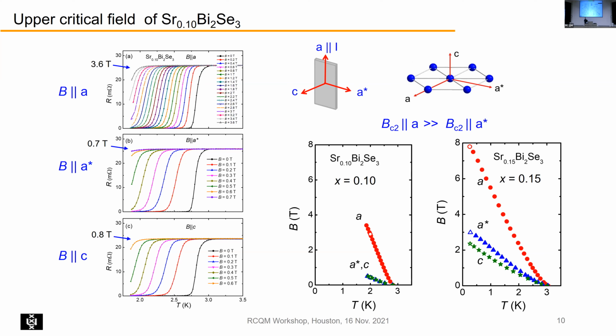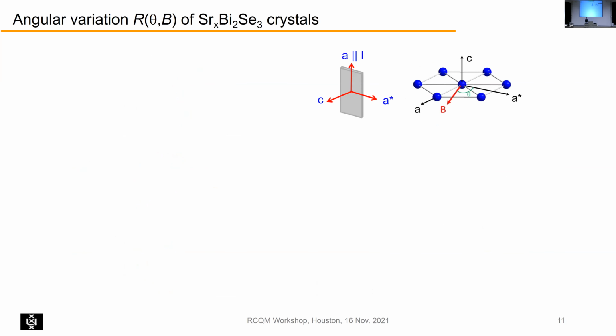Then we said we have to study this better. So let's also look at the angular dependence. We put our sample on a rotator and directly measure how this critical field varies with the angle. Now, from the plane to C, we know that it is normally smaller to bigger, but we also did a rotation for the field in the plane. So we rotate the field like here in the plane.